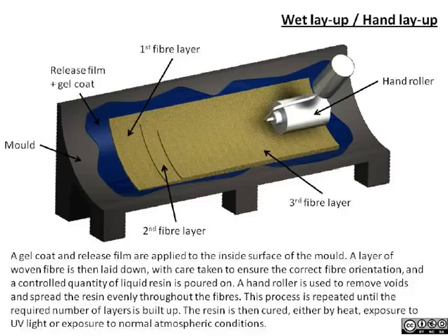This can be adapted to mass manufacturing and rapid manufacturing, but basically it would involve a sheet or a tape of a woven fiber composite, usually pre-impregnated with its polymer matrix, an epoxy or phenolic that is partially cured so that it's handleable, and it's laid up in a mold, or in the case of a tape wrap composite, is actually wound around a mandrel with a release layer, and then the entire assembly is usually vacuum bagged and cured in a hydroclave or autoclave.